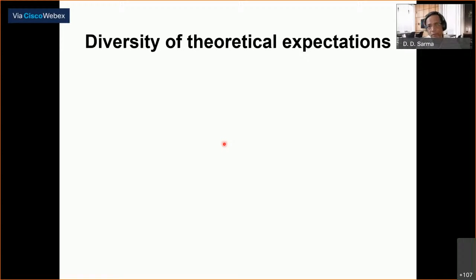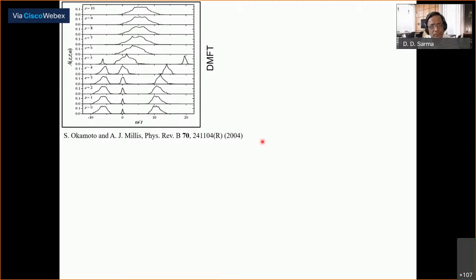What is unexpected is that depending on the theoretical tool that was used, it turns out that the description is very different. This is Okamoto and Andy Millis' work from early on, 2004, using DMFT, and what they are doing is showing you the layer-resolved electronic structure at each of the layers. This top layer is the strontium titanate layers, and these are the lanthanum titanate layers, and this is the interface layer. This is the chemical potential here, and these states here we call the coherent peak. Remember, photoemission will see not this part, only the occupied part, which is on the left. So photoemission, according to this theory, would see changes in the spectral intensity at the Fermi energy, increasing over several layers and then decreasing over several layers.